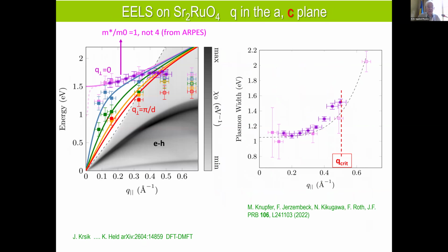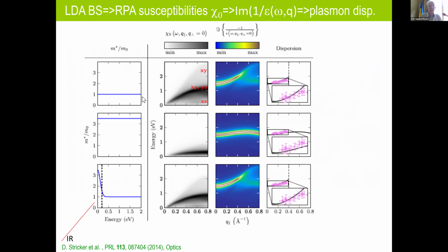And this is the width as a function of the momentum, and we see at the critical wave vector at this point here, the plasmon width diverges because the plasmon dispersion moves into this continuum, which is shown here in black. And this on the right side is a comparison with RPA calculation for different effective mass.